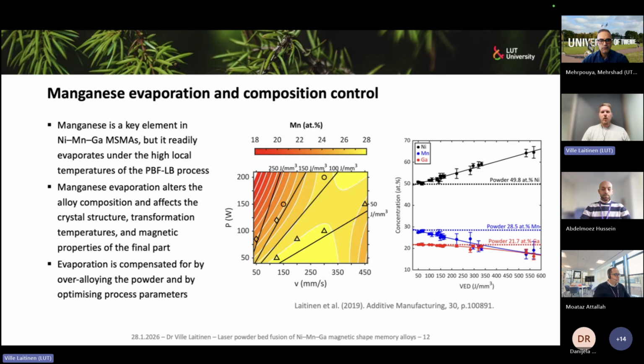So I mentioned manganese evaporation with the powders, and this is very important because manganese in particular is an extremely volatile element in nickel-manganese-gallium. One characteristic is that its boiling temperature is the lowest among the nickel, manganese, and gallium elements. And its vapor pressure is such that in a high temperature treatment, for example heat treatment, or in this kind of high intensity process, we are selectively removing it from the equation. So it very easily leaves the lattice.